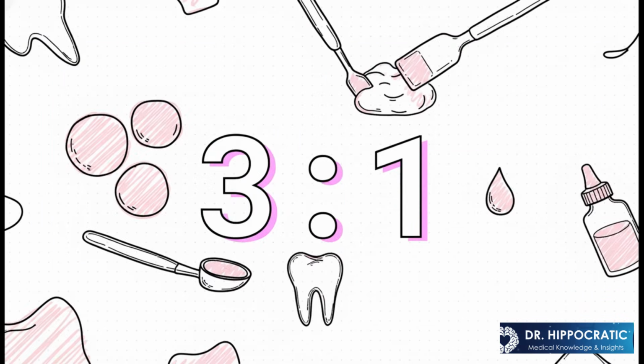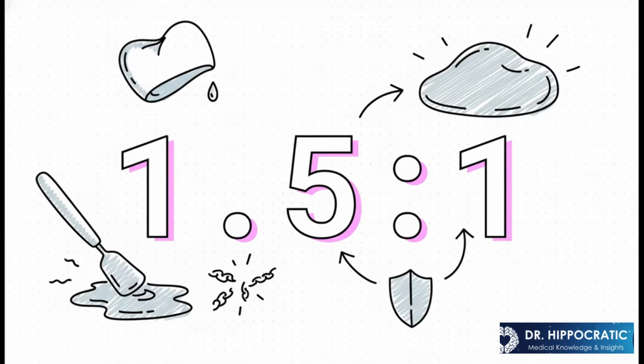Now, not all GICs are made the same. Their strength really depends on the mix. For a tough restorative cement, you're looking at a powder-to-liquid ratio of about 3:1 by weight. Now compare that to a GIC you'd use for luting, cementing a crown. That ratio is way lower, more like 1.5 to 1. It makes for a much runnier mix, and as a result, a much weaker material. This just goes to show how critical it is to get that manufacturer's ratio exactly right.